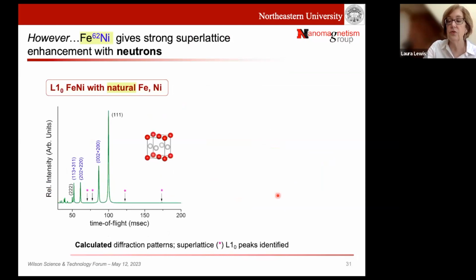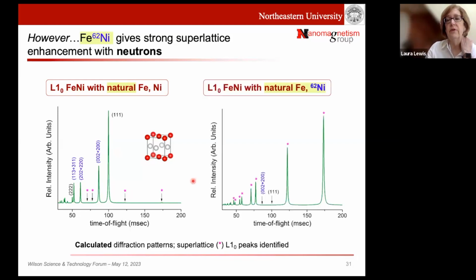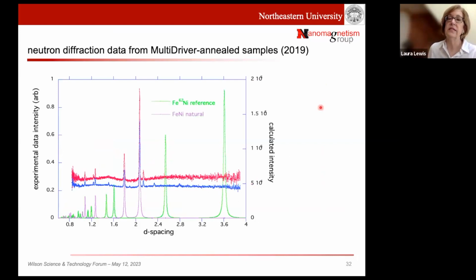Now, if we take this to the neutron facility, what you're seeing here now is what we would expect. These are derived from modeling. If we did natural iron and nickel, still we don't see anything where these peaks are. However, with nickel 62, all we see are those peaks. We don't even see the other ones. So this was what we tried to do, and I'll say tried in a minute. This was data taken from 2019, right before the pandemic and right before this particular neutron beam line was set to be shut down. So we couldn't really get a lot of data.